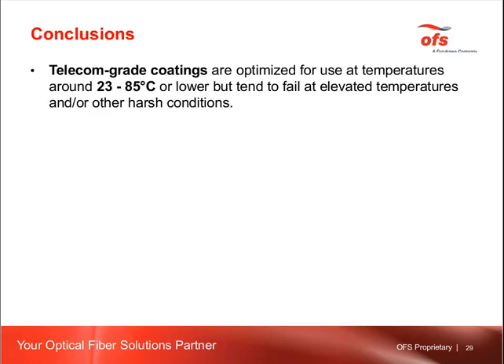And this brings me to the conclusions. First of all, telecom grade coatings are optimized for use at temperatures around 23 to 85 degrees C or lower, but tend to fail at elevated temperatures and other harsh conditions.